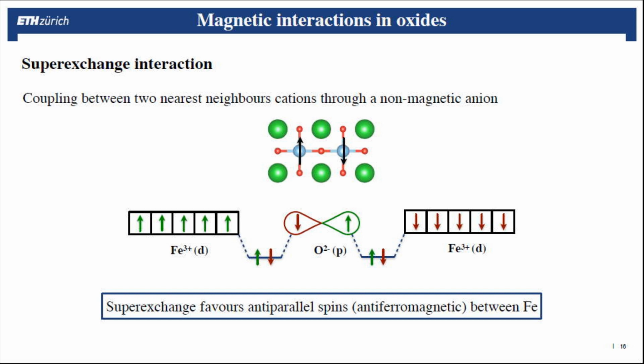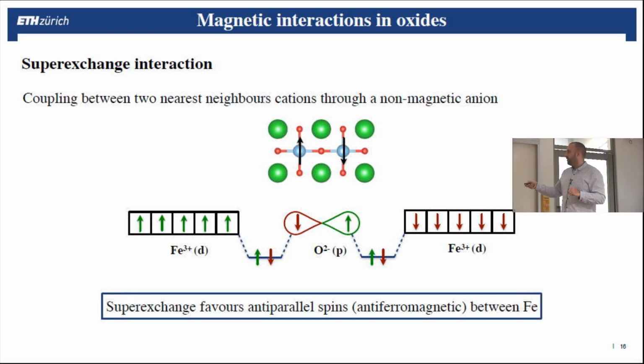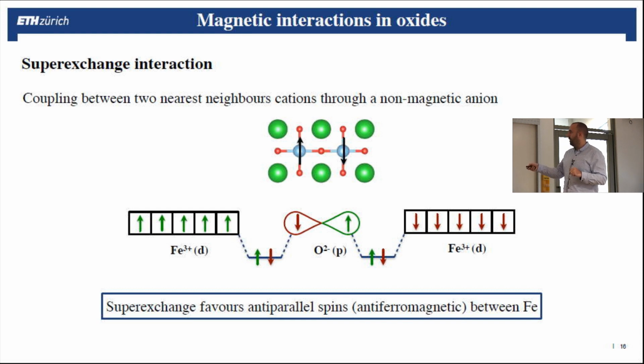Now we said that this one has a bond with the oxygen atom in the middle. As all these spins are up, and according to the exclusion principle, then in the bond you have to get an opposite spin coming from the oxygen. So the oxygen would have, this is the orbital of the oxygen, a spin down in that part. Having this, only one spin remains, and it has to be up. And this constrains the other atom here to be all down, because the up is already taken, so it can only share a down spin. And this means that due to this, the two atoms here will have opposite spins. And that's why super exchange favors anti-parallel alignment of the spins, in this case between the iron atoms.